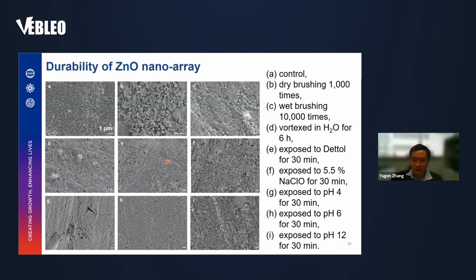And from the results shown here, other than G, the low pH, for all other cases the nano-array structure is basically retained. And even for G, all these surfaces after this durability test have their antimicrobial properties well retained, still demonstrating very good antimicrobial properties.